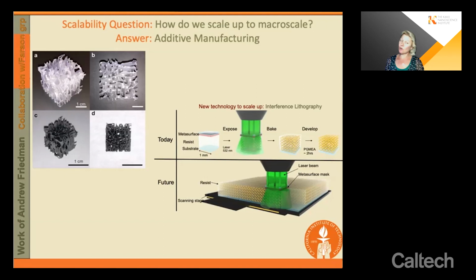Now, it doesn't matter so much if you're creating a sacrificial scaffold. If you're writing something that's a scaffold, and after it's written you're going to deposit something else onto it and then etch it away, it probably doesn't matter very much. But if you're using this kind of chemical synthesis approach to create materials with different chemical functionalities, then you really have to understand the effect of laser power, and not only on the cross-linking in the original resin, but on the grain size formation, for example, or on the specific bonds that are formed after the exposure. So that is definitely a very important factor to consider when creating these materials.